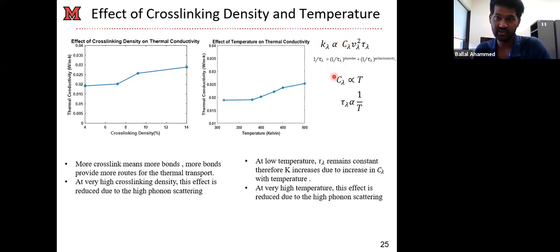But at high temperatures, we know that the scattering rate is proportional to the temperature, so the relaxation time goes down at higher temperatures, which overcompensates the C lambda. As a result, at elevated temperature this K lambda starts to decrease for a specific phonon mode. If you sum over all the phonon modes, it gives a negative trend. So that's the very qualitative explanation for the results that we found from the MD simulations. That's the end of our thermal conductivity study.